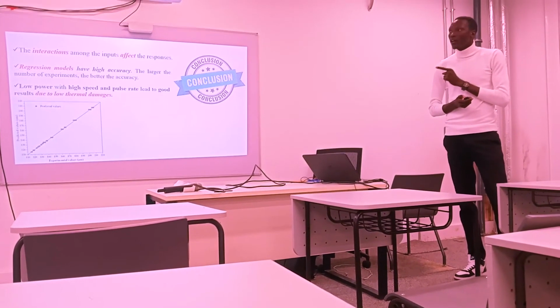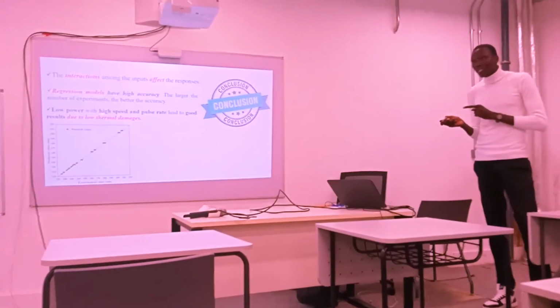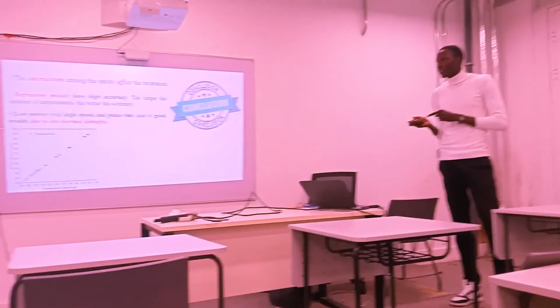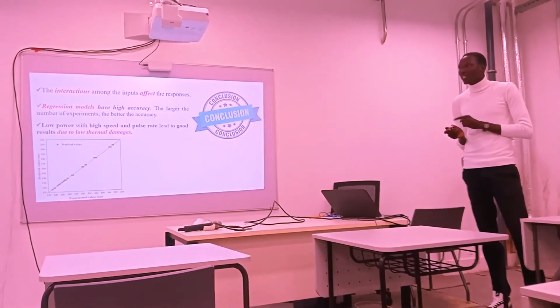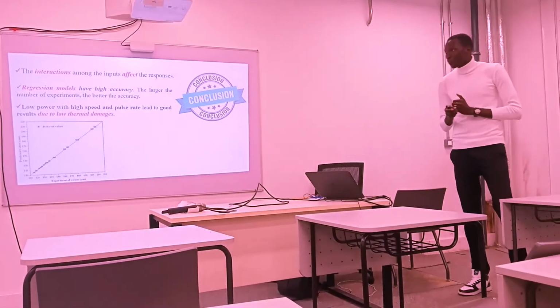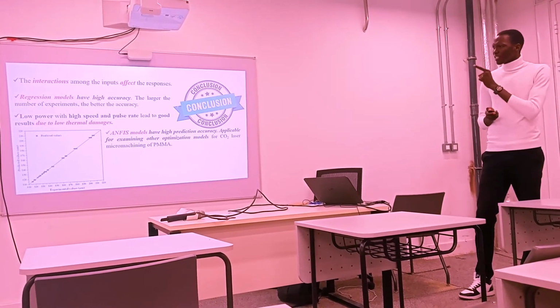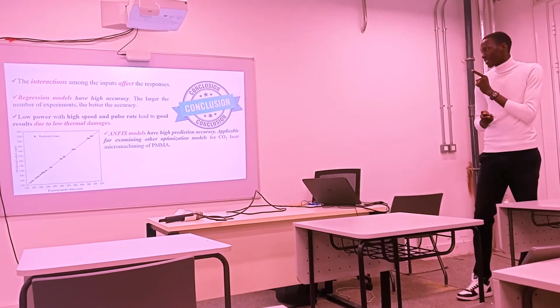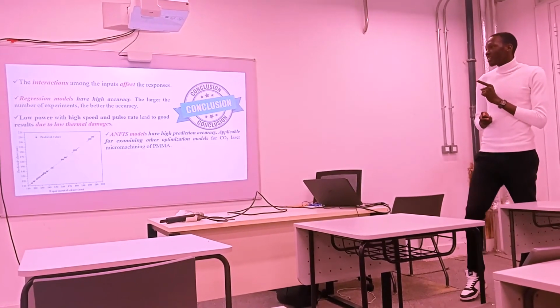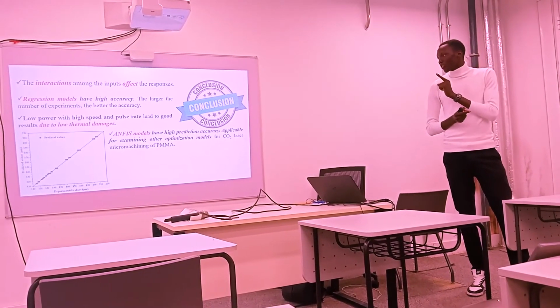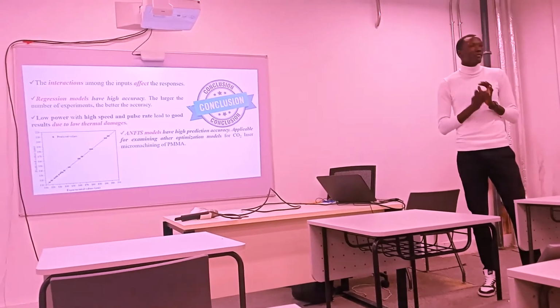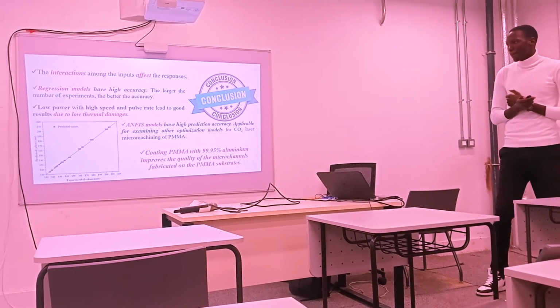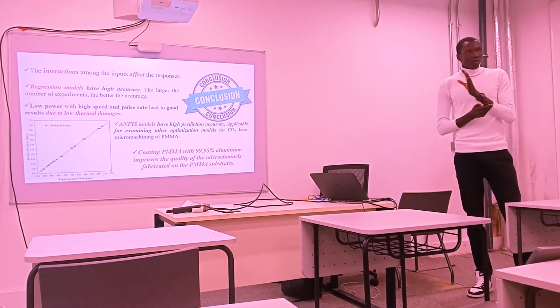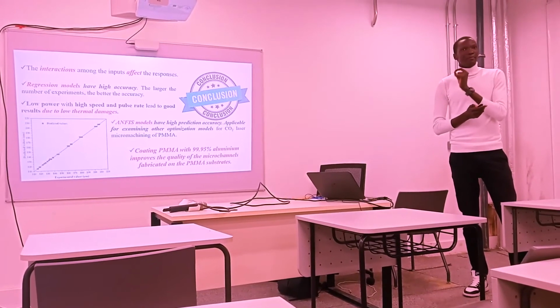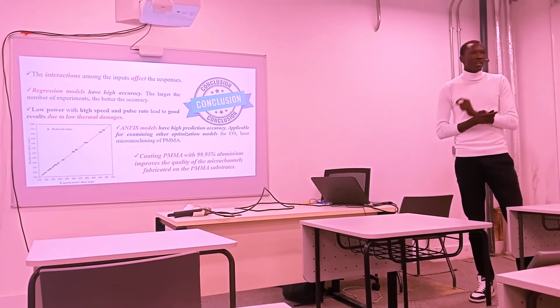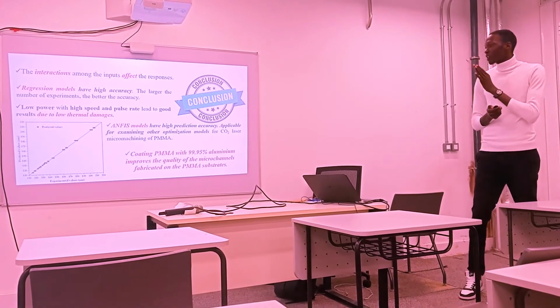Then low power with high speed and high pulse rate lead to good results due to low thermal damages that appear in the ablation zone. Then, the adaptive neuro-fuzzy inference system models have high accuracy. They can be applied to examine other optimization models for CO2 laser micromachining of PMMA, our material. The ultimate conclusion is that coating PMMA with 99.95% pure aluminum improves the quality of the microchannels fabricated on the